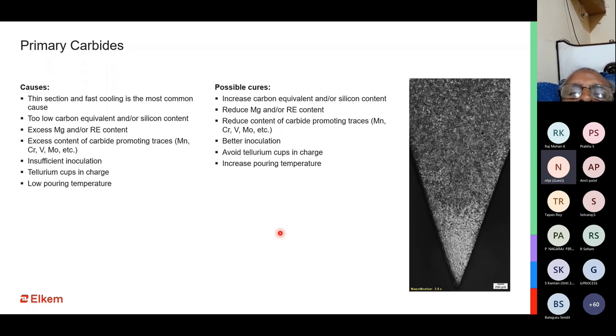We have most of the foundries using CE meters. And in the case of CE meters, we use those white tellurium containing cups. Please make sure that those cups or the metal which is present in the cup does not go back into your furnace. Because these cups contain tellurium at the bottom of them. You would have seen that white colored patch. And this tellurium is a very strong carbide promoter. Of course, many of you must be having this kind of equipment.